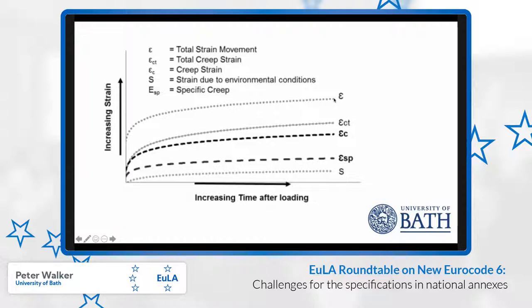But what we report primarily is the creep strain, or the specific creep strain. Just to clarify the differences, this is the strain we measured. Initially, we see an initial elastic strain in the specimens when we actually apply the load. So the difference between these top two curves is the deduction of the initial elastic strain due to the application of the load. So this is the time-dependent creep strain.